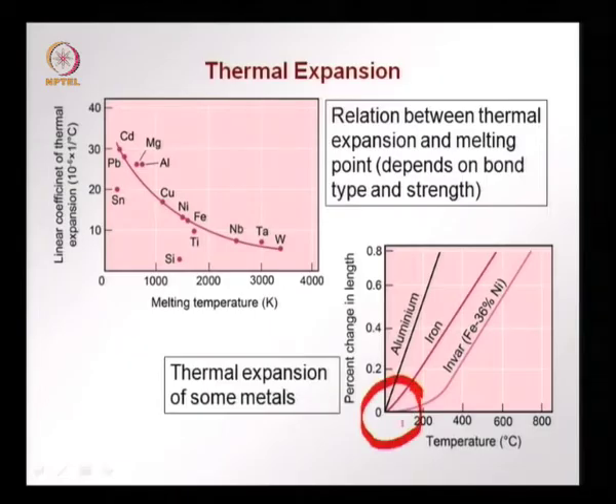We find that over a range of temperature, INVAR does not expand at all, that is the thermal coefficient of expansion is 0 up to a range of say 100 degrees. So, this means that this material will not vary in its dimensions up to a temperature about 100 degrees. That is why we use INVAR as a reference in calibration when we want in the lab to measure change of strains or deformations over a period of time.